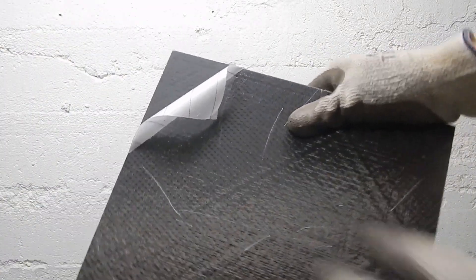And this peel ply, straight nylon peel ply was stuck on there pretty good. But that's normal. I think having faster resin feed would have helped. You can see that biaxial printed in on the top skin. But all in all, it came out pretty nice.